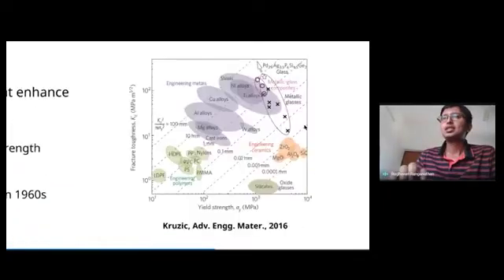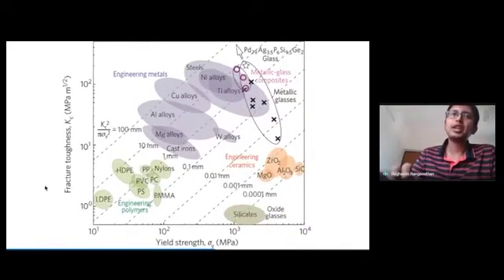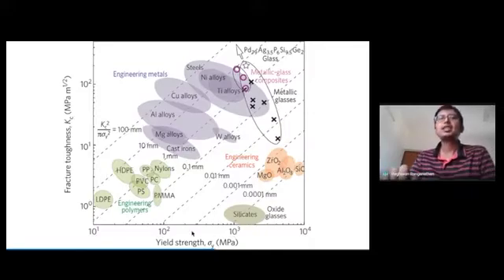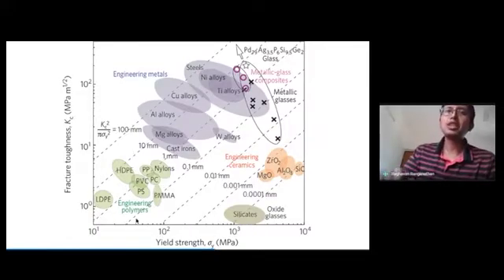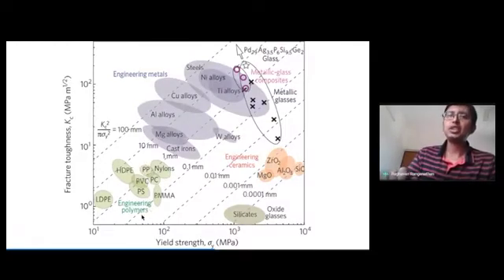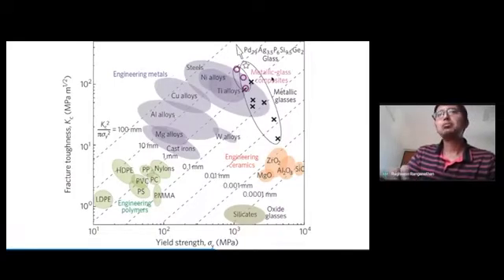And I'd like to show this plot that compares the fracture toughness on the y-axis as a function of yield strength for various classes of materials. What you see here on the bottom left are traditional polymers that have a very low yield strength and a very low fracture toughness. Whereas all these violet bubbles that you see, these are engineering metals that have a very large fracture toughness, but modestly large yield strength.